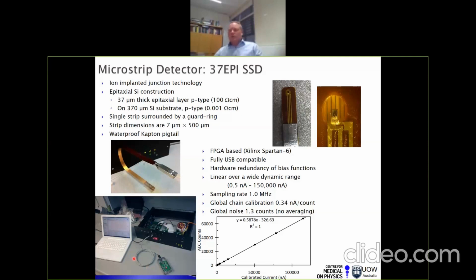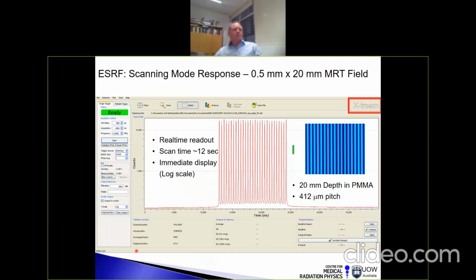Very quickly, one example of that. Here our detector is green, and we can scan that through our radiation field. We've done that here, and this is the output directly from our readout system. It takes about 12 seconds to do this. We're sampling in the megahertz region, and this is on a log scale, so you can see 10,000 counts, 1,000 counts. This is a massive dynamic range that's required here, and we've got these extremely steep dose gradients. So we can examine each one of these X-ray microbeams, these blades of radiation, which are used to treat these very difficult cancers.